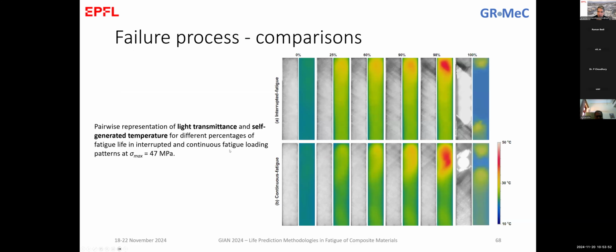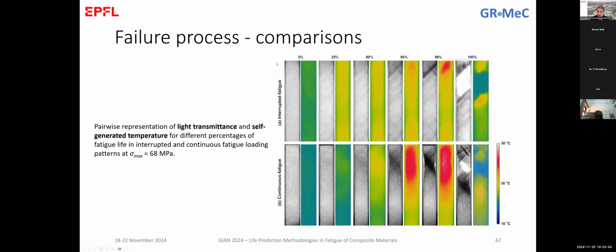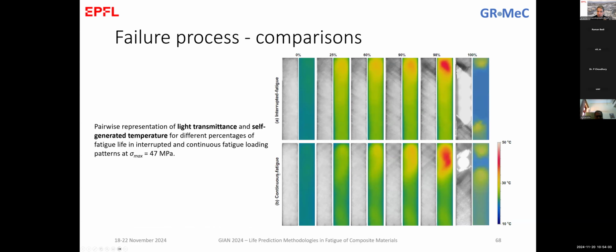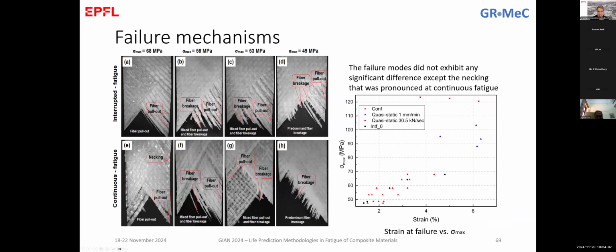And as we mentioned before, the material under interrupted fatigue loading performs as the material performs in continuous fatigue at low stress levels. So there we have the behavior for interrupted fatigue at high stress levels. We have the same behavior of the material as what we have in the continuous fatigue at low stress levels in terms of deformation.